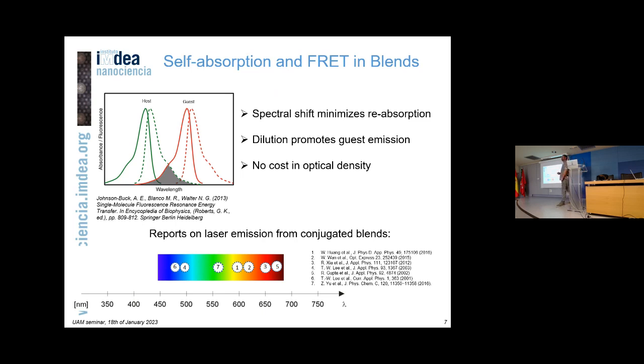But there is an intrinsic problem with organic molecules for lasers: when you have a solid medium, you start to have disorder. You get molecules nearby each other, with different statistical distributions of chromophores, and that means your line shapes get inhomogeneously broader. That means the absorption tail can eventually extend into the spectral region of luminescence, and you get self-absorption. One way to overcome this problem is to use Förster resonance energy transfer.